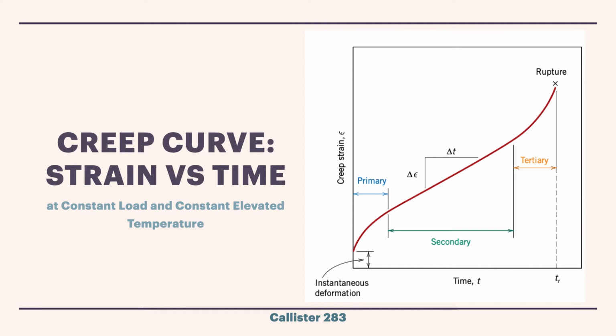The next phase is the secondary creep or the steady-state creep. As its name describes, this phase has a linear slope, during which the material deforms steadily. The last phase is the tertiary phase, which ends with rupture. As can be seen from the graph, the increasing slope signifies that there is rapid deformation, which leads to rupture, such as grain boundary separation, cracks, or even cavities.